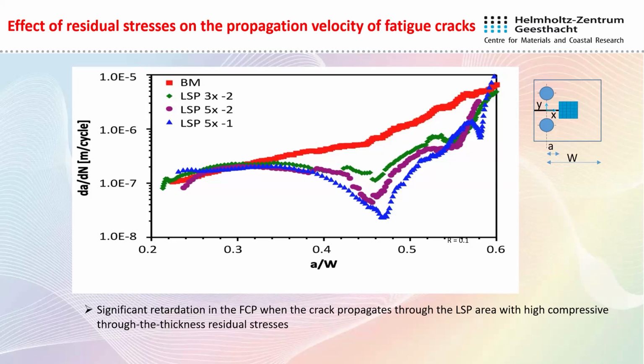About 3 years ago, I started to work in laser shock peening. I have very good friends in Germany. They developed this technique for Airbus, and they told me, you're working with fatigue cracks. There is a very good technique to drive the fatigue crack propagation. Could you try? And he showed laser shock peening results from his colleagues from Germany.